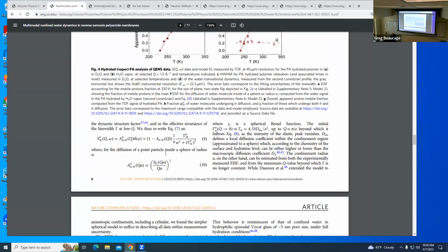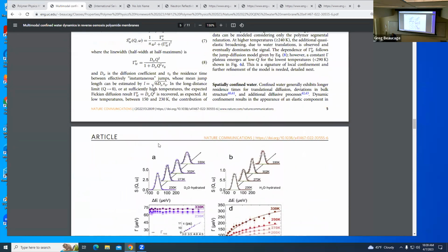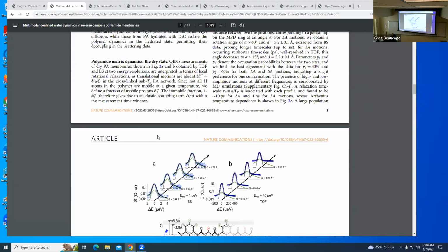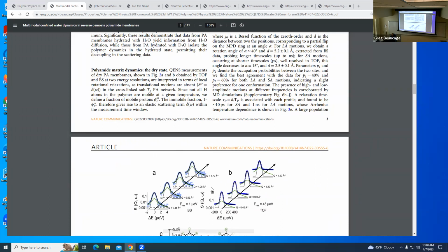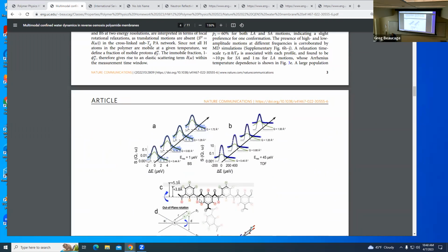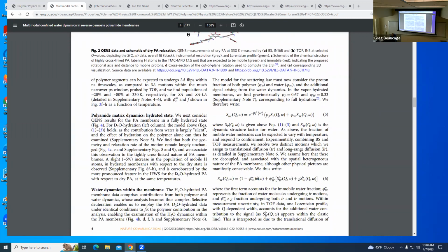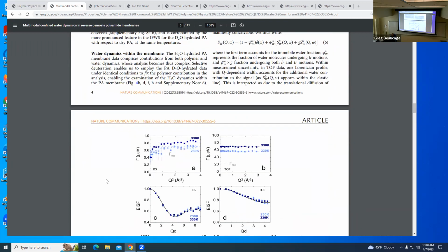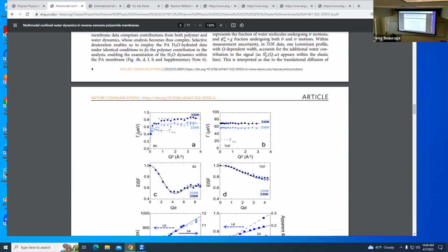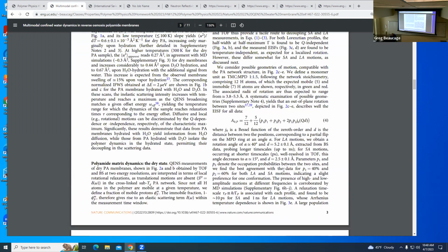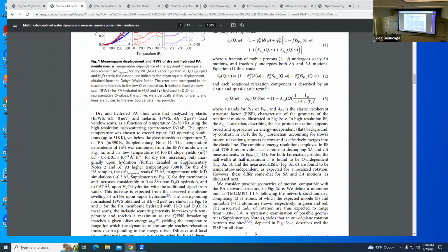Right, so there's a lot in here. He goes through a lot of different analyses, breaking this into the bulk transport term. First he does the polyamide, and these are the things he talks about, basically the rotation of that difunctional ring. The other ring's kind of fixed because it's tied three ways. But he's got the spinning relaxation of that, and he discusses that ad nauseam. This is the gamma from the Lorentzian function, wherever that is. So that's that gamma, which is the half width.